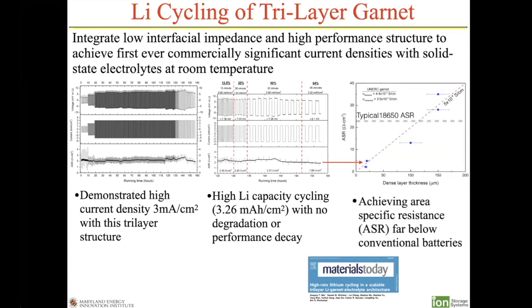The figure to the right is a plot of the area specific resistance for these symmetric cells versus the thickness of the dense layer. The dashed red line is the conductivity of the garnet, and the blue data is various different thickness samples that we made. You can see how well they fit that line. What you're seeing is just the ohmic ASR of these things.